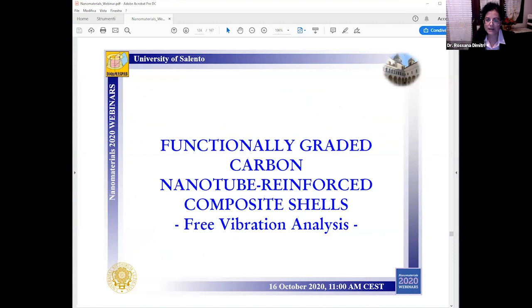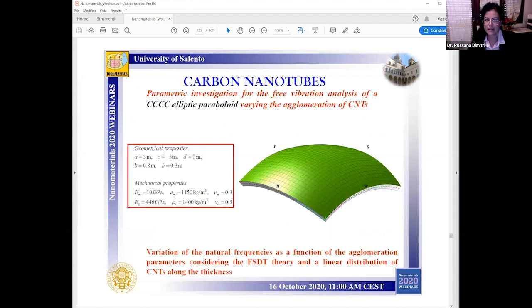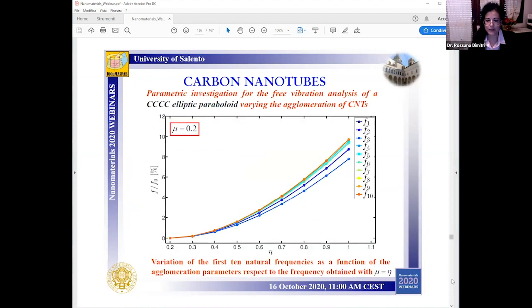So now, as a numerical application, let's discuss the free vibration response of a completely clamped shell for different agglomeration parameters of carbon nanotubes. In this example, we assume a linear distribution of carbon nanotubes along the thickness, where we apply a first order shear deformation theory under a fixed geometry and fixed mechanical properties of the matrix and of the reinforcing phase.